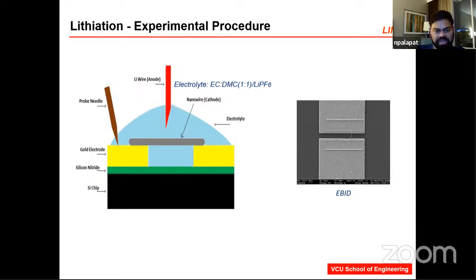So in all my experiments, I've performed an unlithiated test. Then I performed lithiation at 2.75 volts, 2.25 volts, and 1.5 volts, with degradation studies at each of these lithiation cycles, and performed different characterizations to measure the electrical, electrochemical, and mechanical properties of these nanowires.